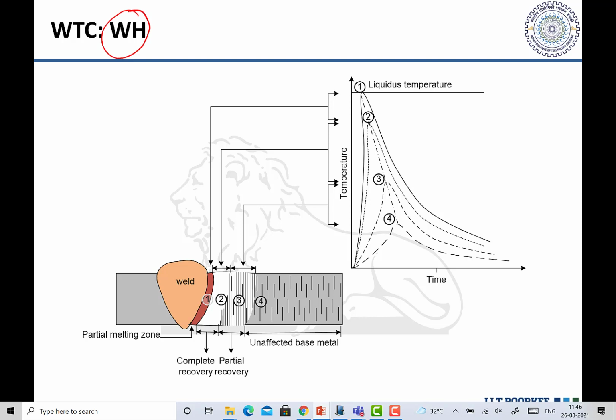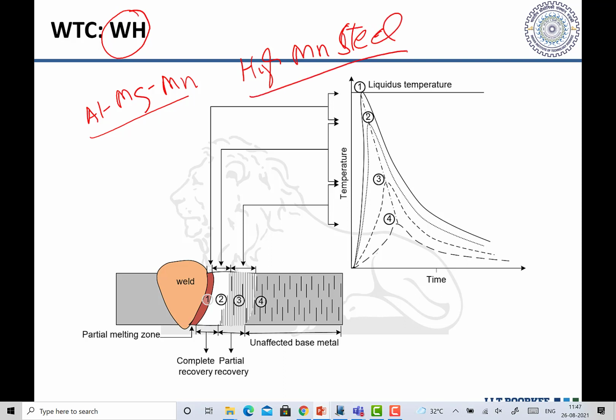Metals strengthened primarily by work hardening, in aluminium alloys like, say, aluminium, magnesium and manganese, are one kind of typical system strengthened primarily by this. And there are other systems like high manganese steels. Those also get a lot of their strength from deformation and work hardening. So you see, the base metal which has been strengthened by work hardening is full of dislocations, right?